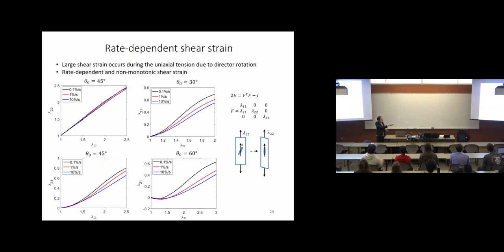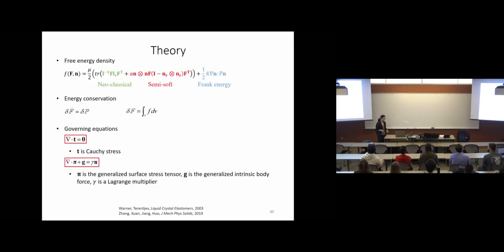First of all, we compare the result from DIC for the stretch in the stretching direction. For different loading rates, indeed, it should be equal to whatever you apply externally. Moreover, we observe this large shear strain for all those different tilted cases, and those shear strains are also rate dependent.